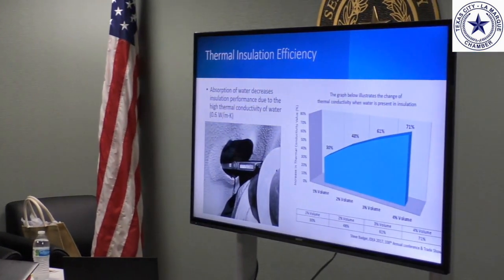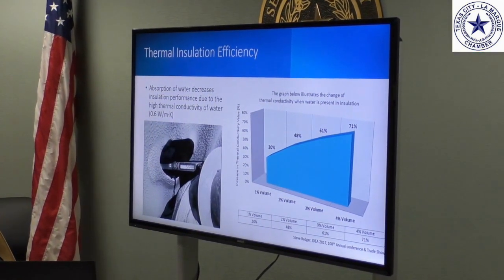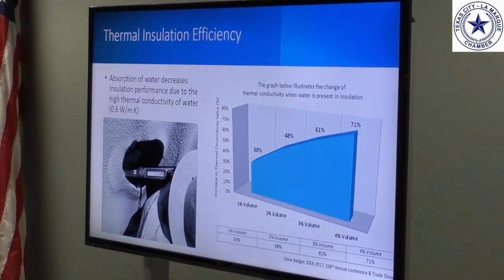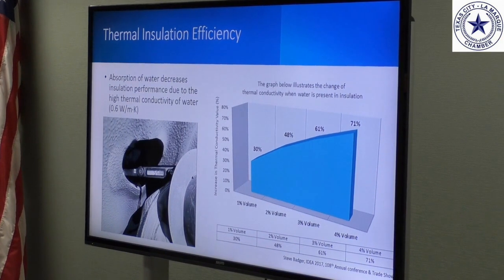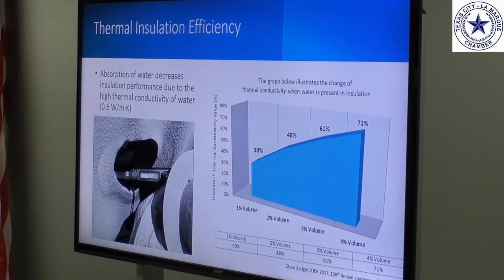Now, thermal efficiency. It is thought that when mineral wool is installed, it has a very low thermal conductivity, and it does. It's rated at 0.04, 0.05 watts per meter Kelvin, but that's dry, and it's never dry. So we measured moisture at one of the inspection ports with one of our development partners. So we partnered with companies to develop this technology, and it allowed us to measure moisture in mineral wool on one of their tanks. And if you notice, it's measuring 5% moisture.